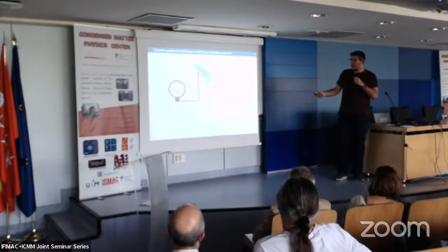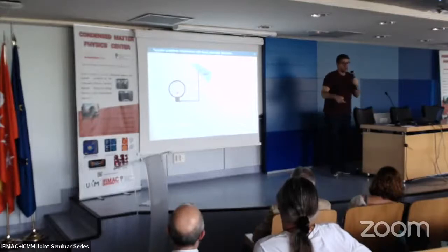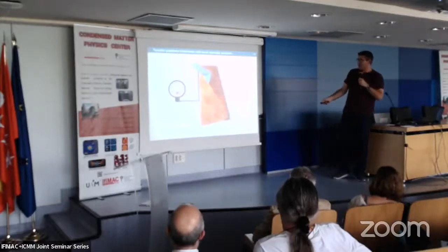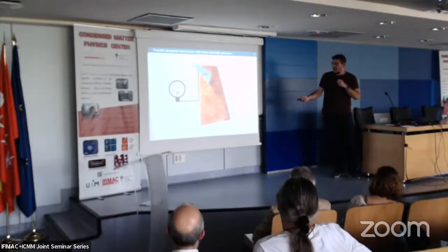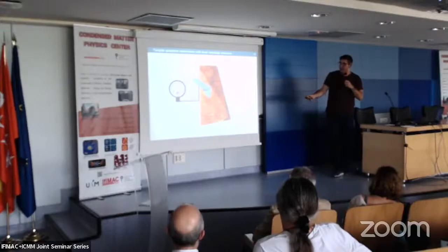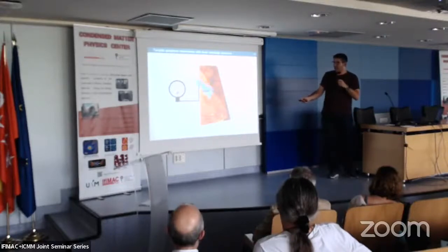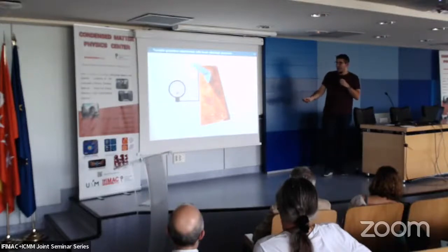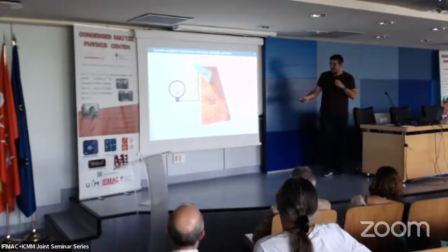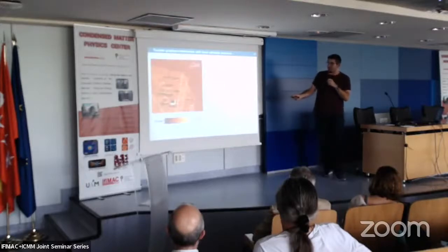We have our tip in the AFM working in a mode typically called dynamic mode or tapping mode. The tip is oscillating far from the surface, so we are not putting pressure on it. With this, we can just visualize our sample. This is just a part of a graphene sheet. Now when we want to modify it, we bring the tip into contact, put in a pressure set point, and now we can scan the tip at this pressure in a given area. When we finish that, we bring the tip back up to tapping mode, and we see the effects. We can see that this area has flattened and sunk, and we have modified it with this pressure. We can do this at different ultra high pressures.